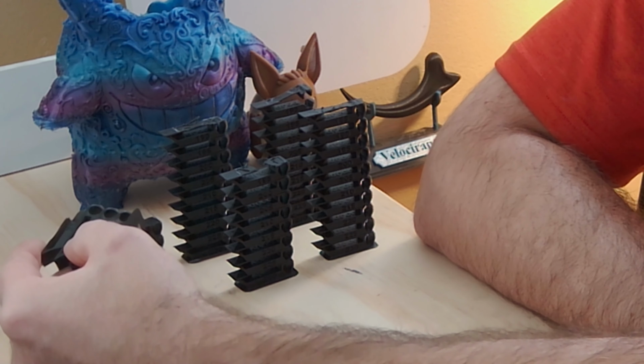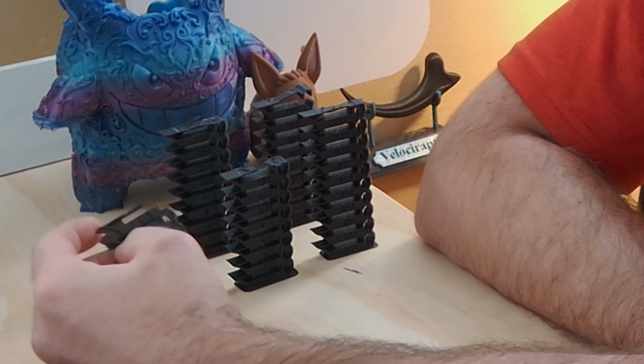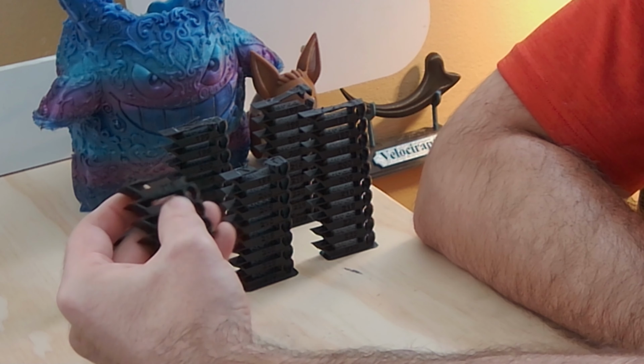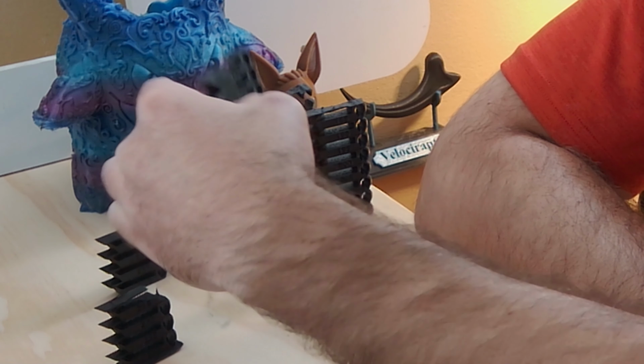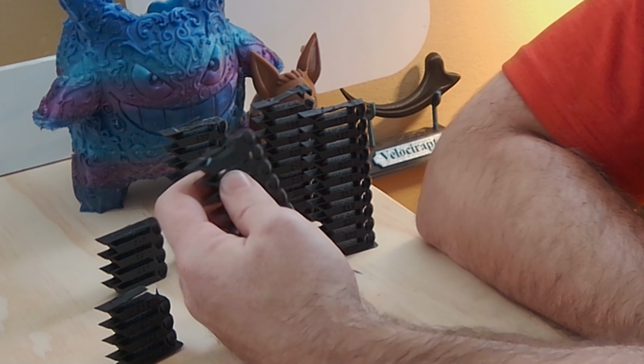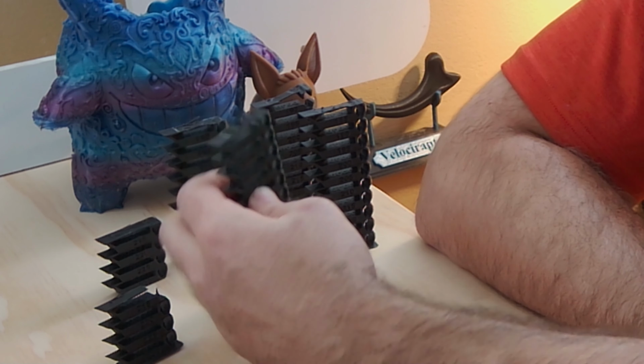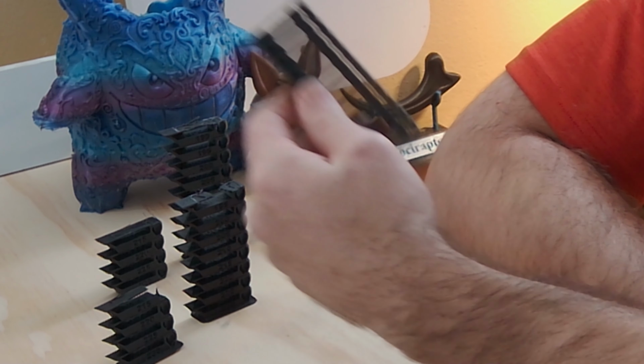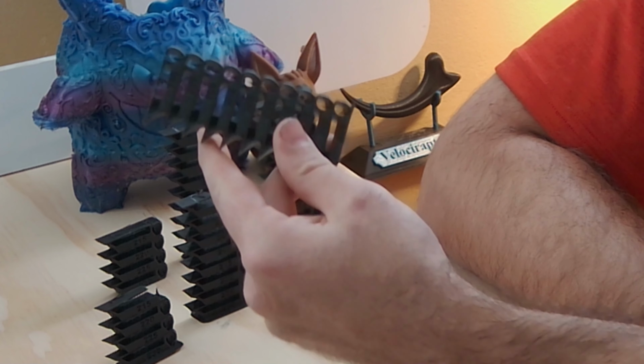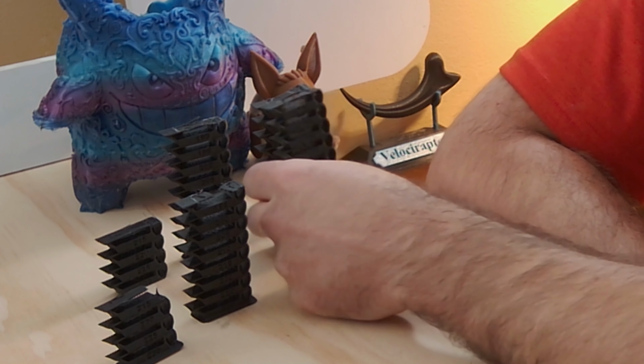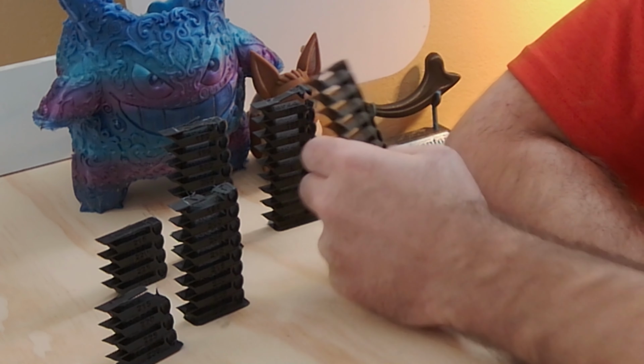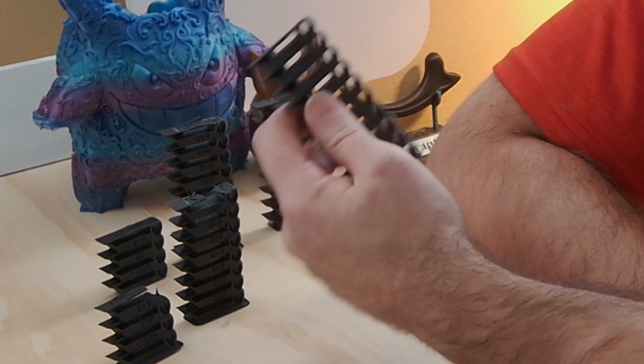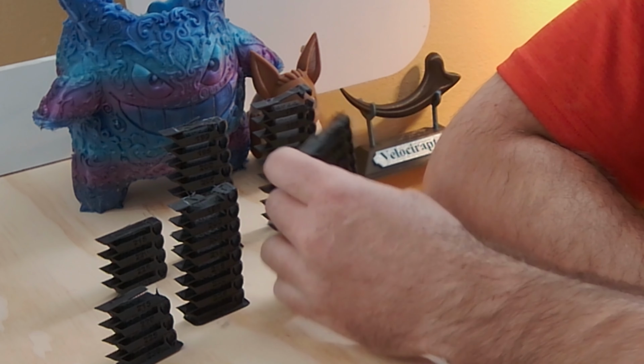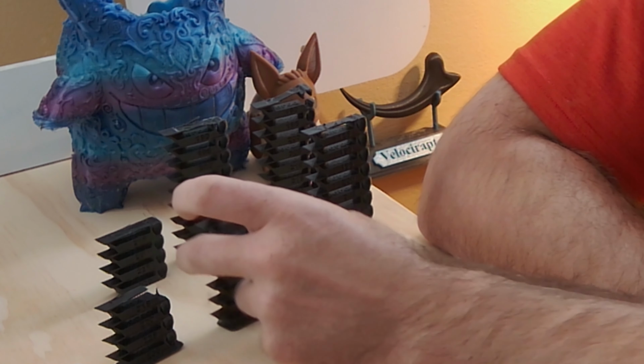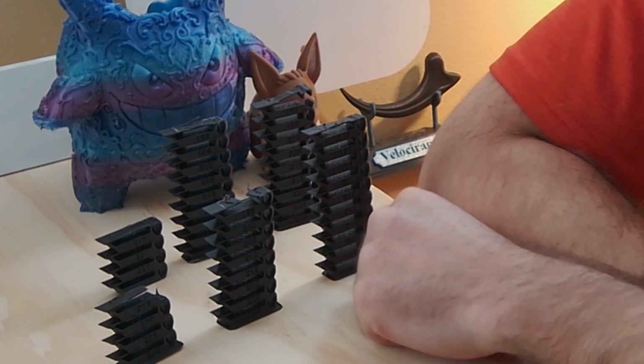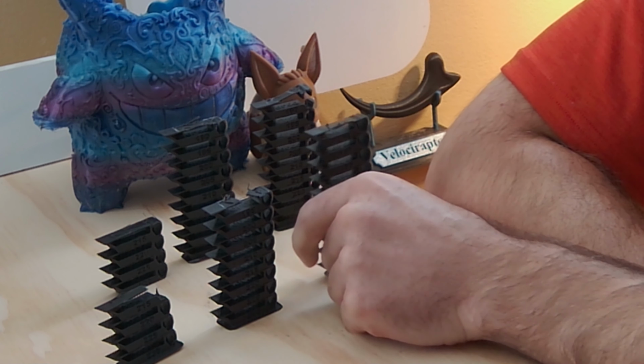So next here is going to be the Red PLA. Hardened, I did have to go to 215 to really have any strength. I was able to go clear down to 195 here with the nickel-plated copper, and then the Red PLA, interestingly enough, was stronger than the Creality Hyper at even clear down to 185 degrees. This part has a lot of strength in it. So again, Diamond was able to improve the performance of the cheaper filament by quite a large margin.